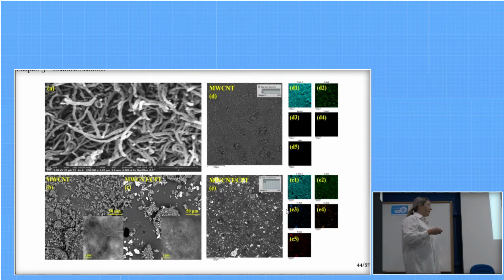And then we analyzed, similarly to the last study, the formation of pure carbon in the sample, and that the addition of the chalcopyrite here caused these particles to repel themselves. Then we show an even distribution and the appearance of copper and iron elements in the sample, as well as a decrease in carbon content after the incorporation.